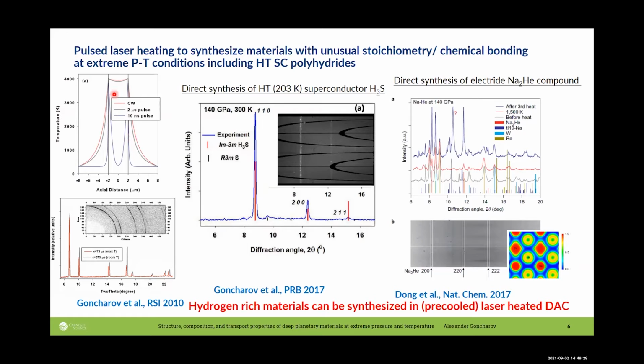And in this case, you can see that you can have a thermal temperature distribution very close to continuous heating. So essentially very low temperature drop in the middle of the sample. And we performed this experiment.